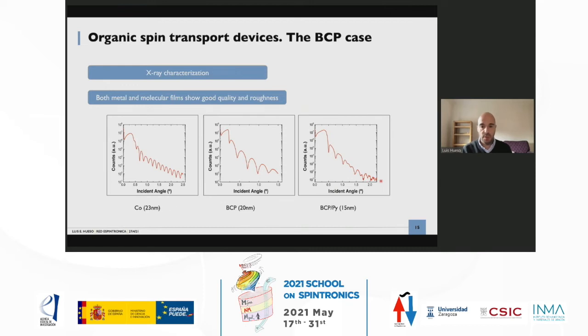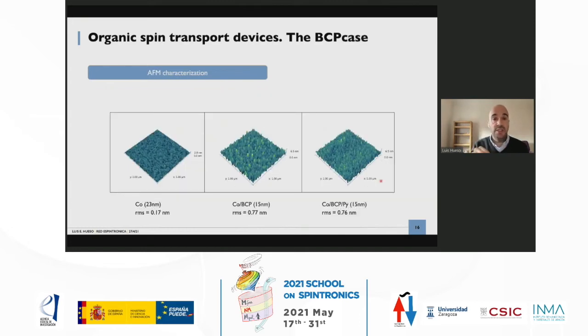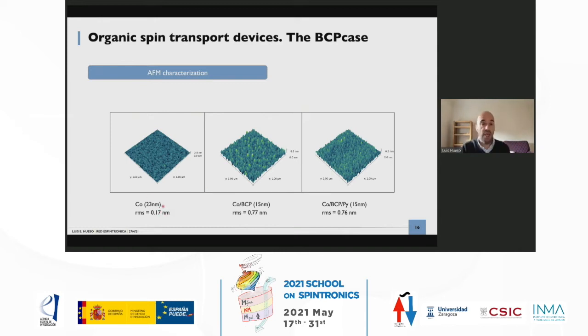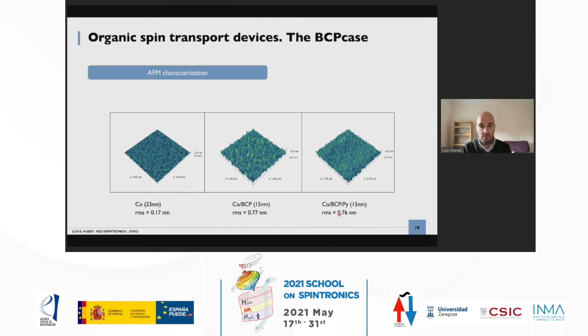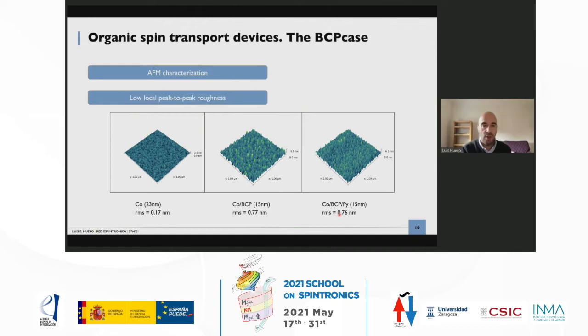We do X-ray characterization first, because it shows us the quality of the devices. You can do a grazing-angle X-ray of the cobalt and see many oscillations — each oscillation occurs because at a different angle, the incident beam hits the bottom and top of the cobalt, creating an interference pattern. The more interference fringes, the better the quality — the more parallel the bottom and top surfaces. There's a very nice interference pattern for the cobalt, for the molecular layer, and even for the permaloy on top of the molecule. Devices are about 10 by 10 microns in size — macroscopic devices, with nothing nanoscopic except the molecule itself.